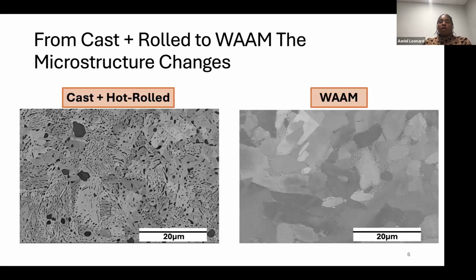When we look at wire arc additive manufactured nickel aluminum bronze versus a cast and roll system, some of the things you can really see is that the microstructure is coarser. And one thing that happens in the cast and roll conditions is you get these large, globular, asymmetrical shaped precipitates known as kappa 1.